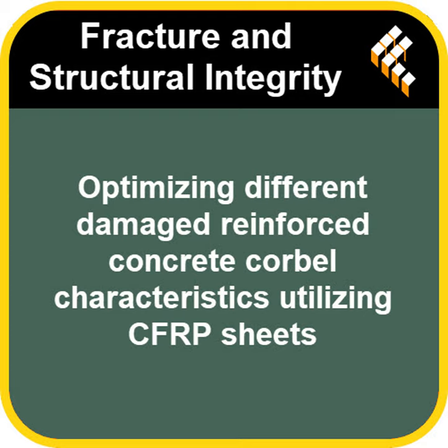Right. And interestingly, across all damage levels, the side wrapping consistently resulted in slightly higher stiffness, about 3 to 5% more than the strip wrapping. So side wrapping seems better for controlling deformation too. That's what the data indicates, yes. Superior deformation control. Okay, so we have increased load capacity, increased stiffness, especially with side wrapping.